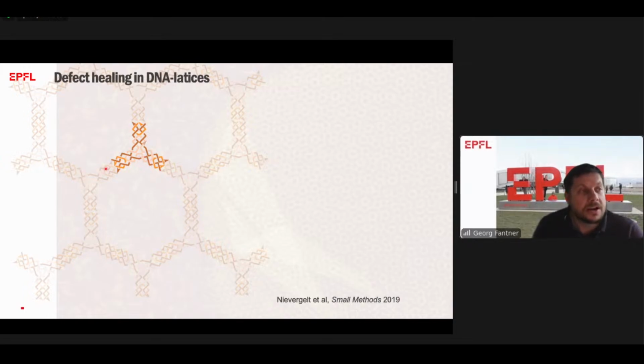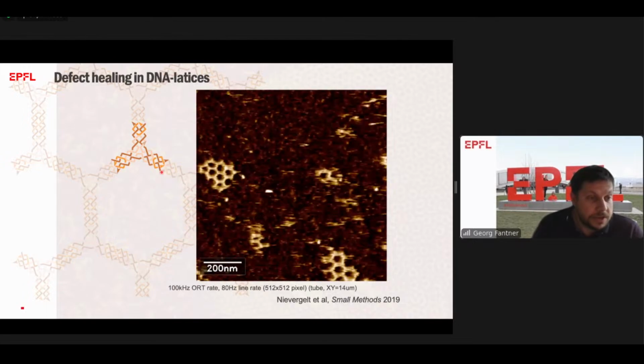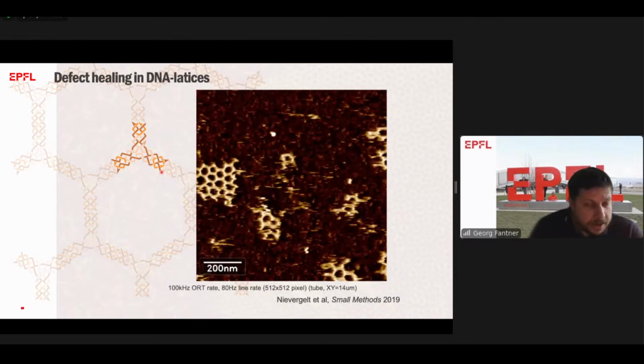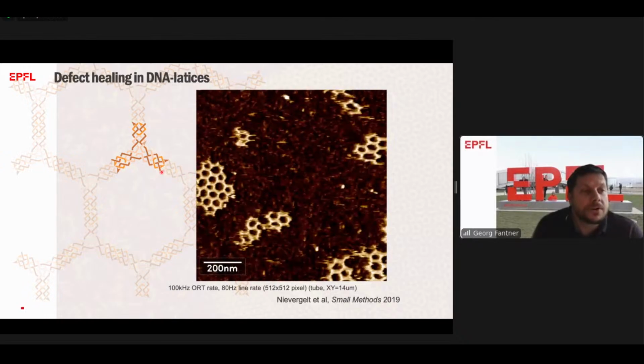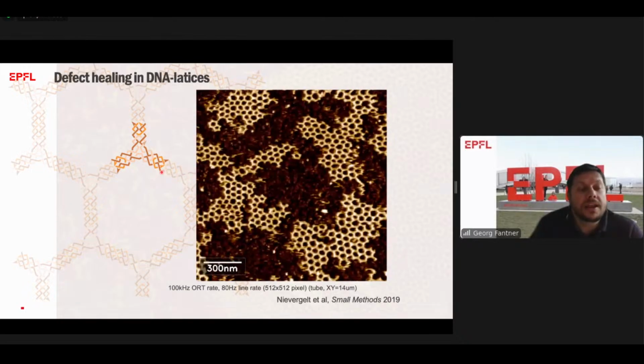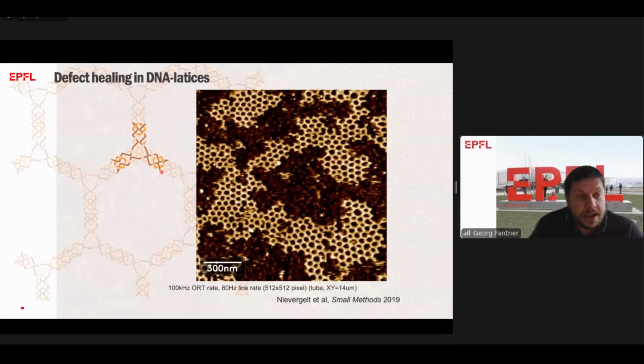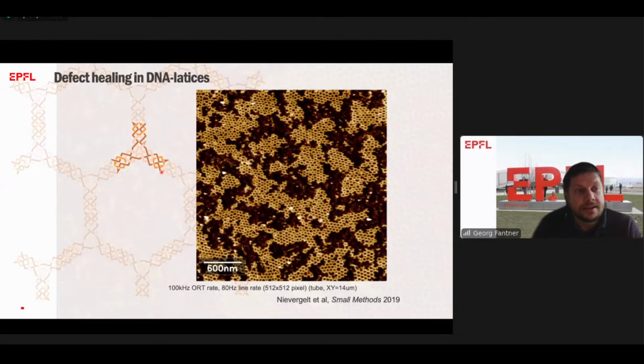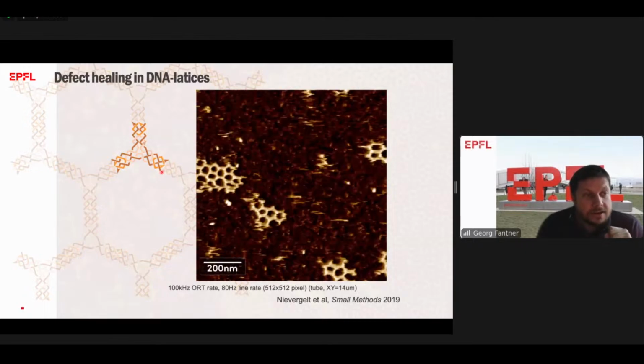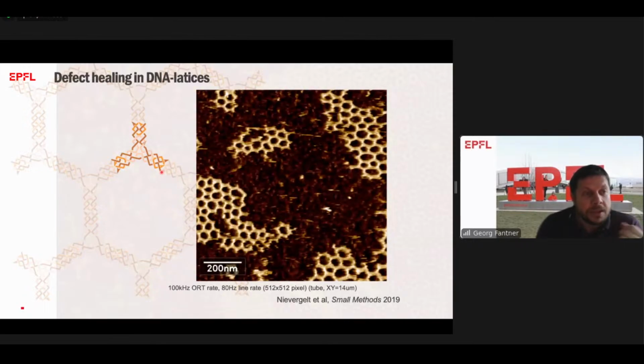Depending on how strong this blunt end stacking interaction is, how flexible the individual arms are, and how long these arms are, you will get different formations and different defect correction mechanisms. And that's what we're currently studying with this high-speed AFM. This was our very first paper that we published back in 2019, more of a proof of principle that we can record larger areas at the same high speed, look at the individual molecules as they assemble, and also see individual defect corrections.